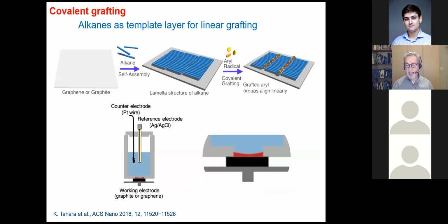Now, we thought maybe that's actually a good thing, because if we try to tune this in a rather clever way, or by just being lucky maybe, we might have an additional control to nanostructure the covalent grafting on the substrate. And we reasoned that maybe the weakest spot, if you have an alkane layer, is the very small space between two of these rows.